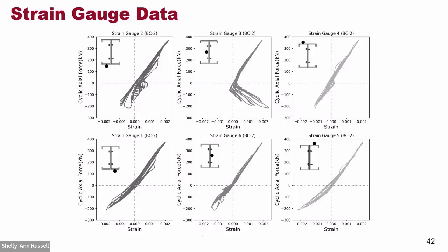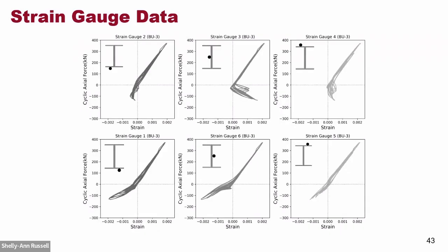From the data analysis of the strain gauges, we can observe that both sections were effective during the cyclic axial loading. So you can see the peak loads. But we have a bit of strange behavior here. It's likely due to the cyclic loading, so critical elastic buckling happens here. Despite the loading being on the negative side, meaning compression, the strain was positive. So we have bending of the web. So it just has these positive strains. And these are the flanges and webs and also flanges. The same thing happens here for the U sections for all these strain gauge data. You can see this section worked more in outward buckling, and this section worked more in inward buckling mode.